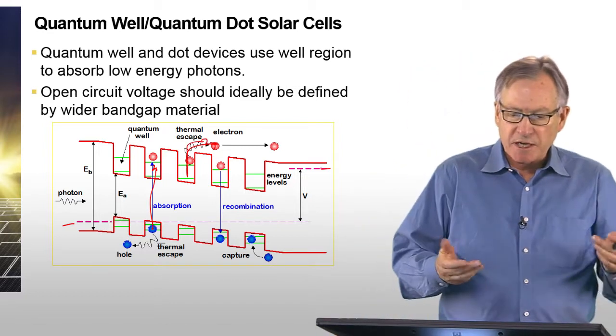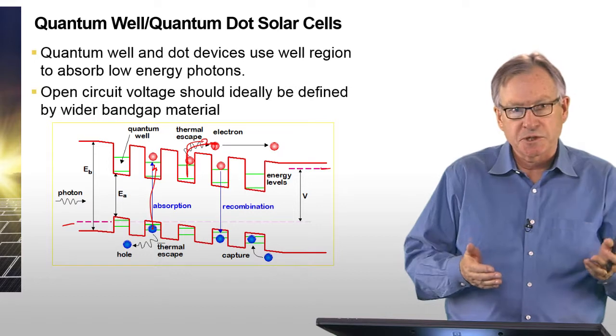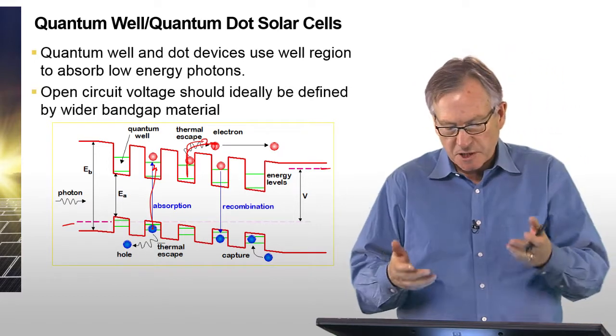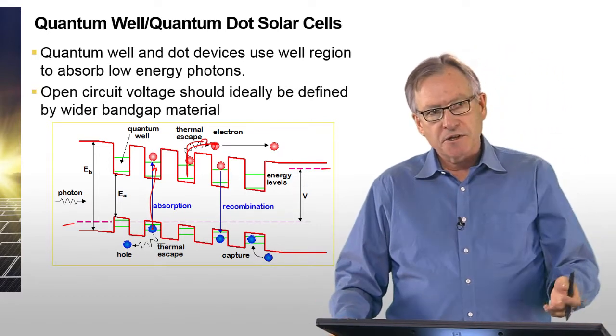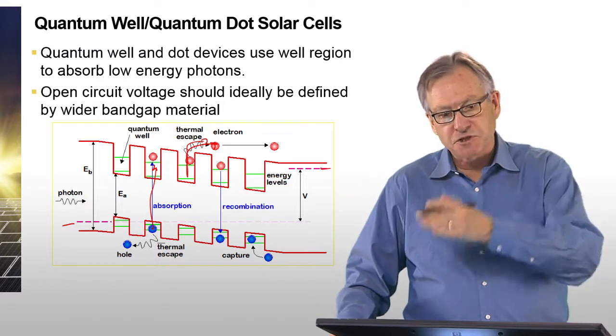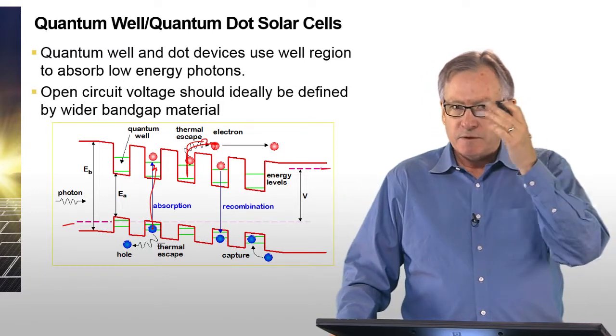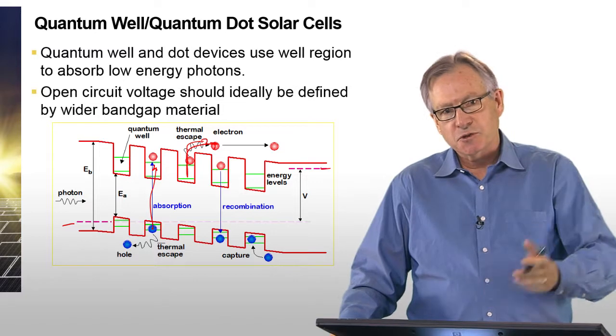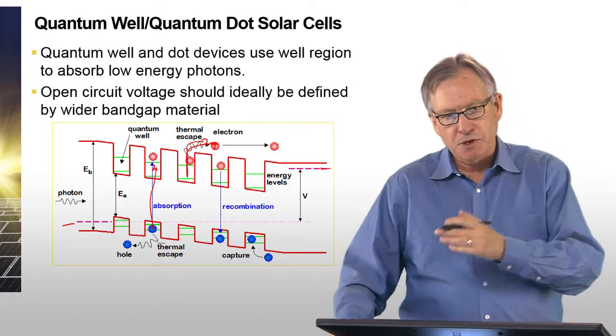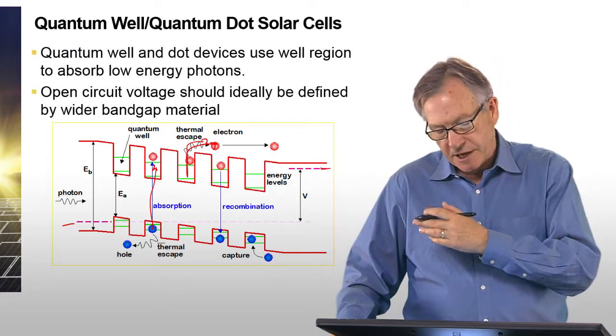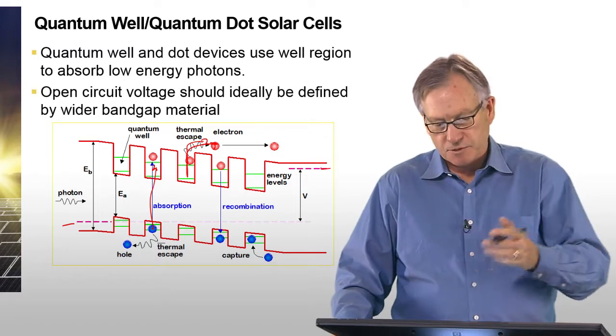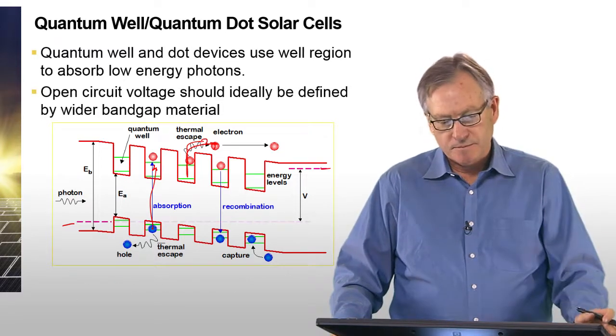So this quantum well solar cell has an architecture similar to an intermediate band solar cell. And ideally then you should have an improvement of efficiency because, while having the open circuit voltage associated with the gallium arsenide material, you get more carrier collection and higher current, which would lead to a higher efficiency.